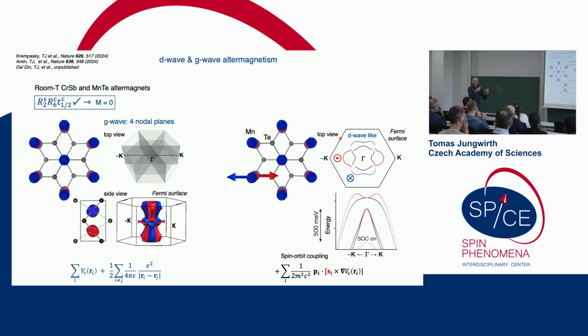It's just because of adding spin-orbit coupling. Now your electrical currents can depend on spin. Again, it will depend which way you apply bias, but it will start to behave like a D-wave altermagnet because of the spin-orbit coupling. So this was so challenging or intriguing to experimentalists that they wanted to see it, and now not in transport or a spintronic effect, but directly by spin-resolved photoemission, ARPES.